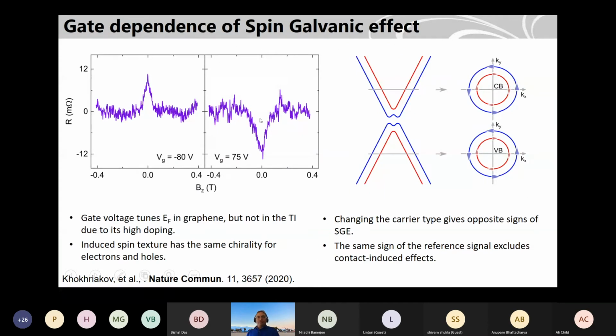Then, to understand what is happening, we wanted to do the gate voltage dependence. At minus 80 gate voltage, we are in the valence band, and at plus 75 gate voltage, we are in the conduction band. As expected, what we see is that the spin directions are the same in this band in the graphene, but we are dealing with electrons and holes. This is for holes, this is for electrons, so the sign should change. This indicates that the spins are coming from the graphene band structure.